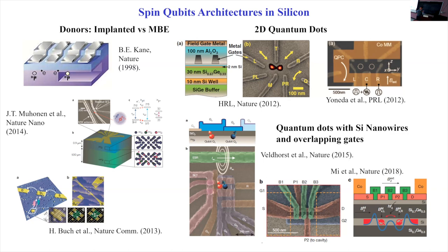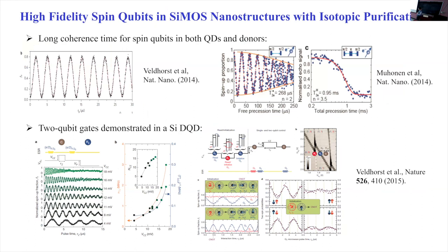With the overlapping gates, you can make the dots larger or smaller, because you're putting the metal gates on top of each other. Okay, but with all these different schemes, people have made a lot of progress in silicon dots. For example, this was with isotopically enriched samples in silicon. This was a silicon MOS type of sample from back in 2014 and 15, almost 10 years ago, where you can see the contrast and fidelity of spin rotations in those samples, in both quantum dots and donor spins, and also coupled two-spin dynamics, also with pretty high fidelity there.